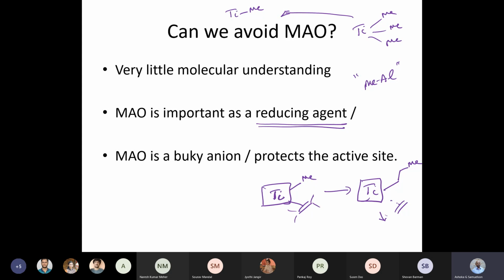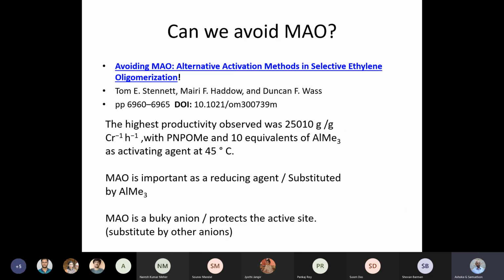which will keep proceeding. So very often MAO has now become an integral part of the polymer industry, and people use it for activating polymerization catalysts also. What I have shown you in the first two slides, or in the first two reactions, is a case where they have used it for the dimerization and the trimerization reactions. Tetramerization has proven to be a lot more difficult, and avoiding MAO is also extremely difficult, and that has been heavily, like I said, heavily researched. Here is a paper which uses 10 equivalents of AlMe3, and it is seen as a breakthrough in the oligomerization of ethylene.